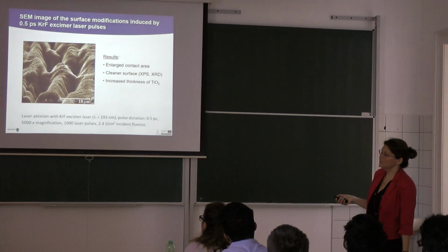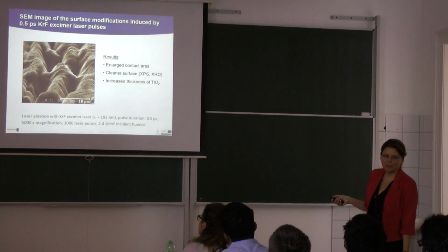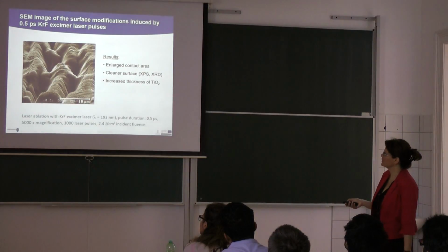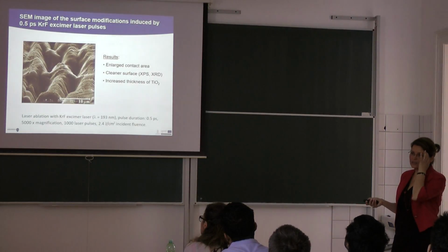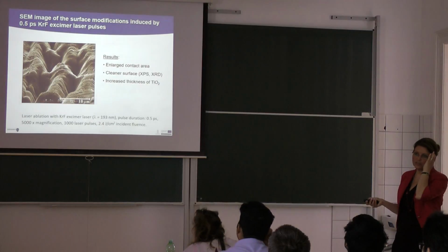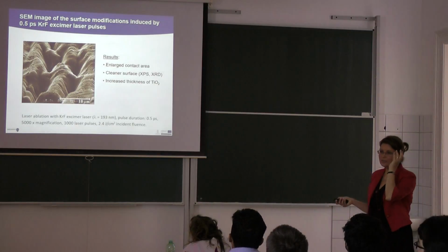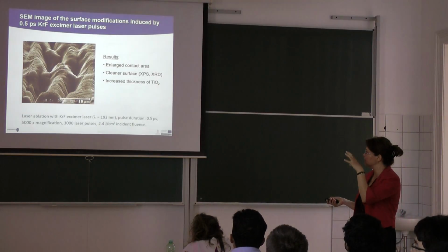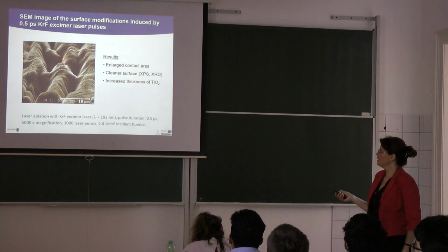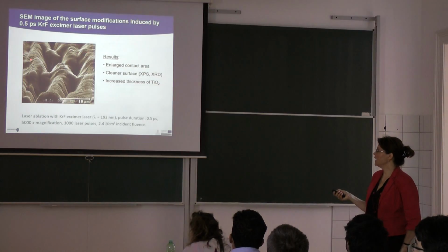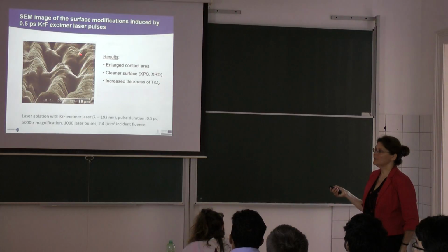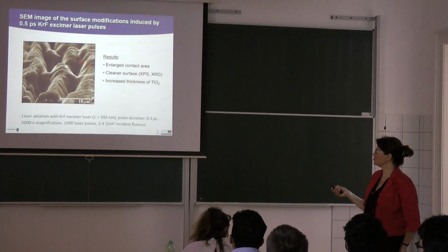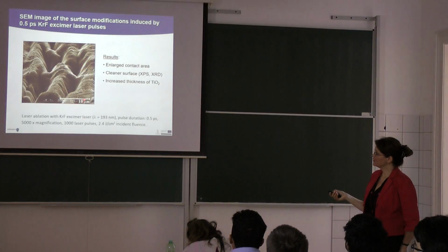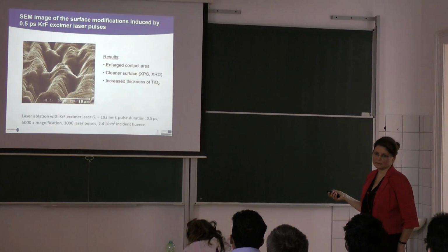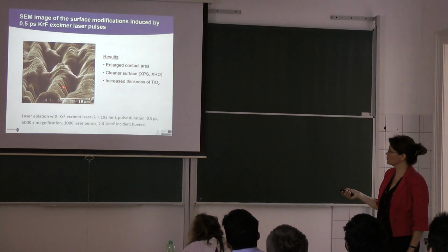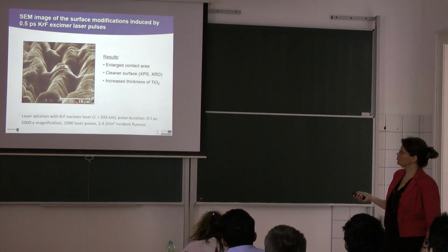And then we went to the big shot, the 0.5 picosecond krypton fluoride excimer laser. Of course, this is a very sophisticated technique because you can use it just in vacuum, so it takes a long time to make a surface area like that. But we could show that we had a large contact area without rims. Yes, so this is much nicer. And the size is very much preferred by the osteoblasts. It's around 10 micrometers, which is the size of these cells which have to attach.